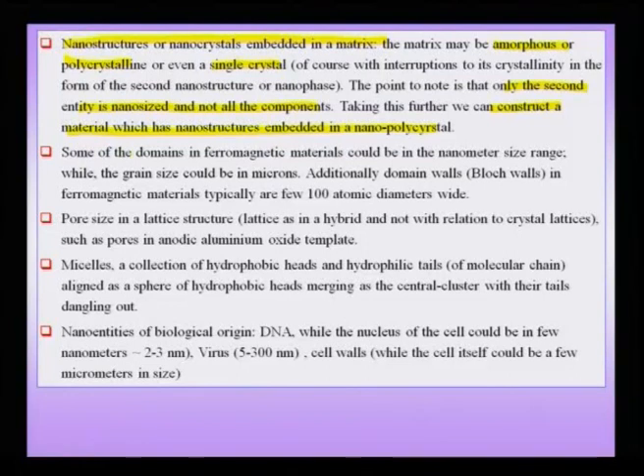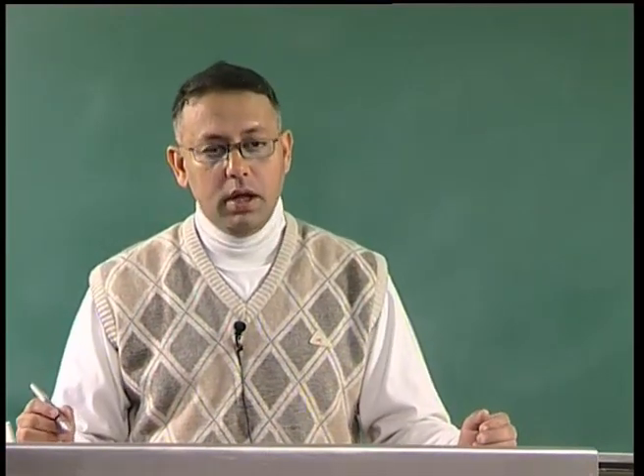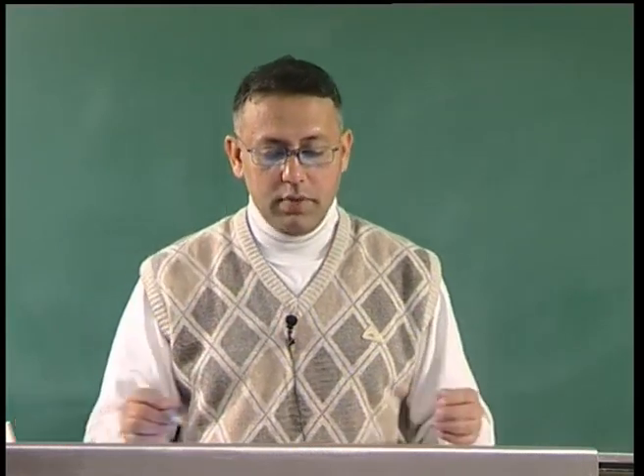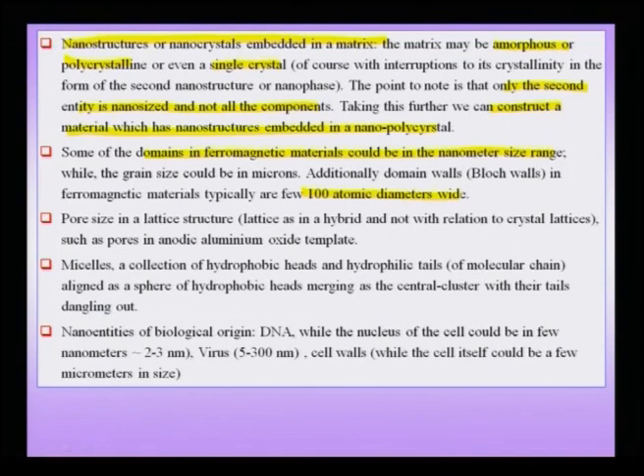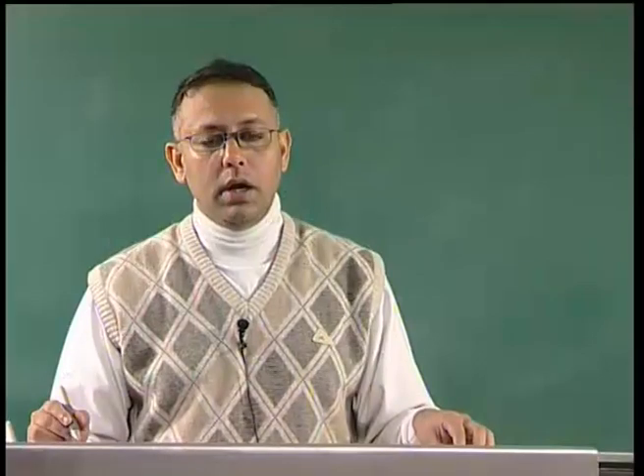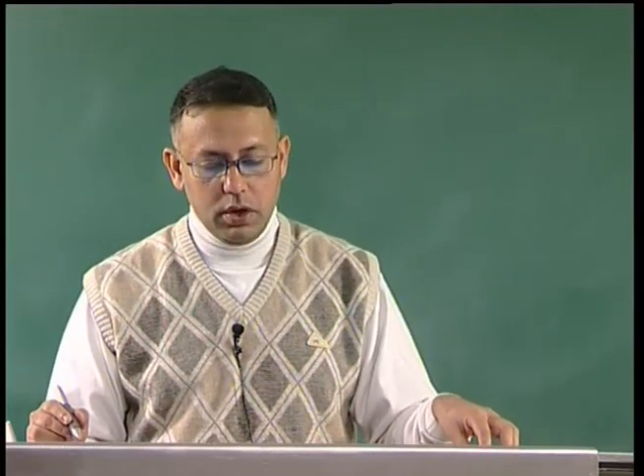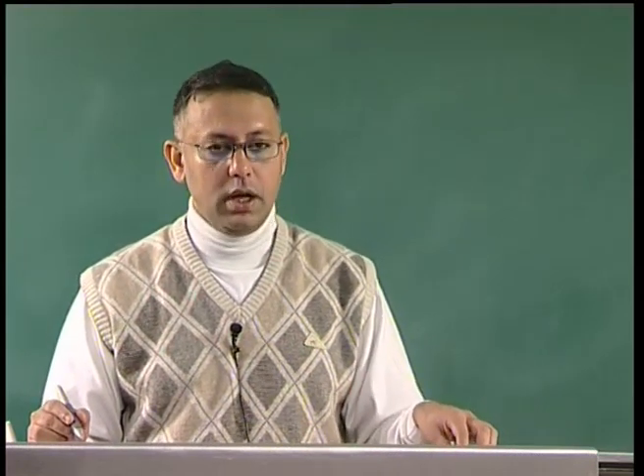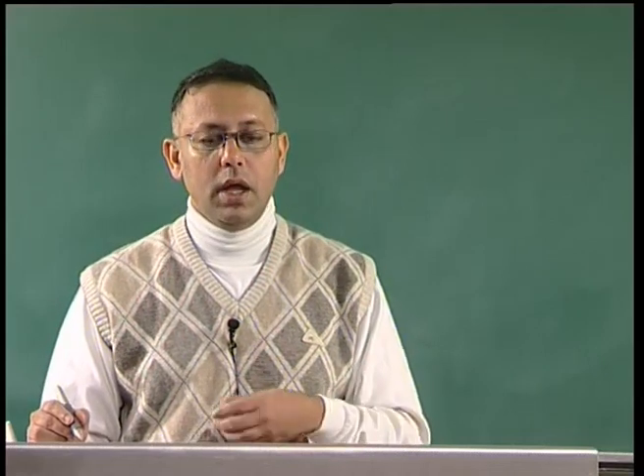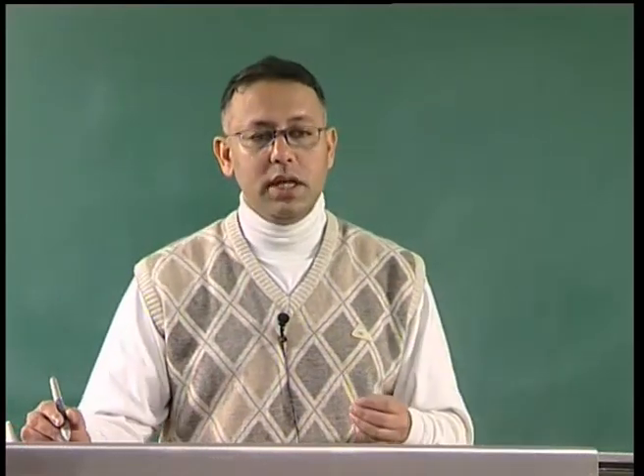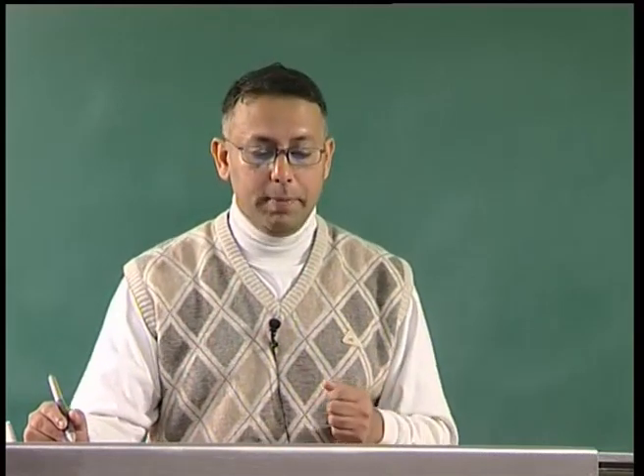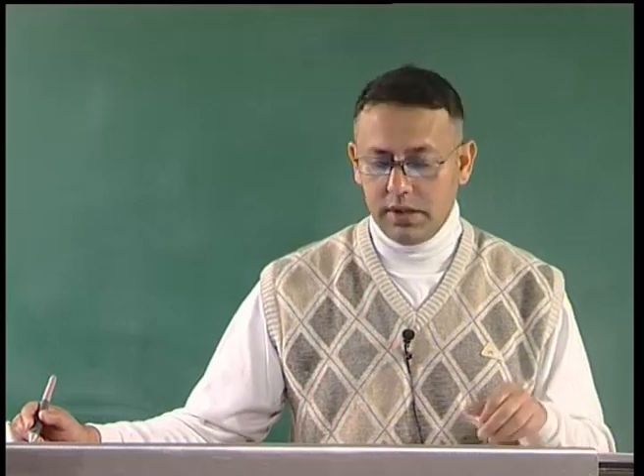Another example: some domains in a ferromagnetic material could be nanometer-sized while other domains are extremely large in the micron scale. Even in a large domain-sized material, domain walls — typically called Bloch walls — have a width of about 100 atomic diameters and are therefore in the nano scale. Even if a ferromagnetic material has grain size and domain size in the microns, it could have Bloch walls at the nanometer length scale.